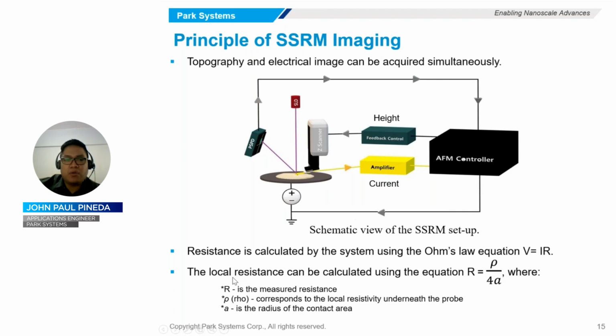So by knowing the resistance, one can also calculate the local resistivity by using the equation R equals rho over 4a, where R is the measured resistance and rho corresponds to the local resistivity underneath the probe, and a is the radius of the circular contact area. This equation was derived by solving the Laplace equation for the electrostatic potential.